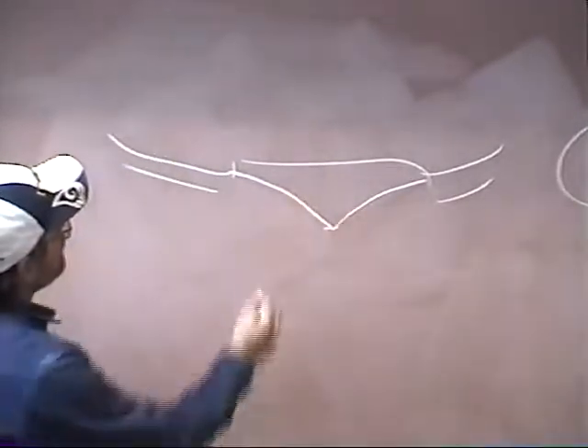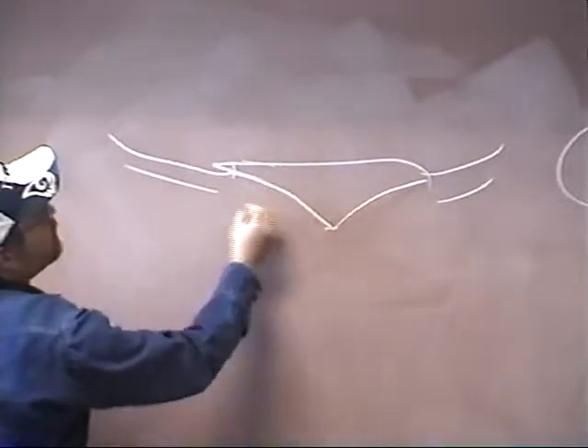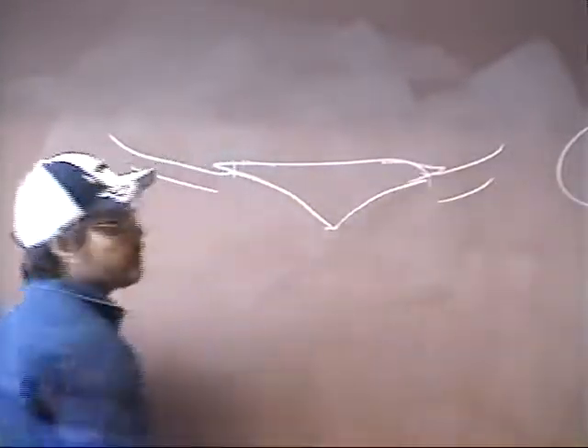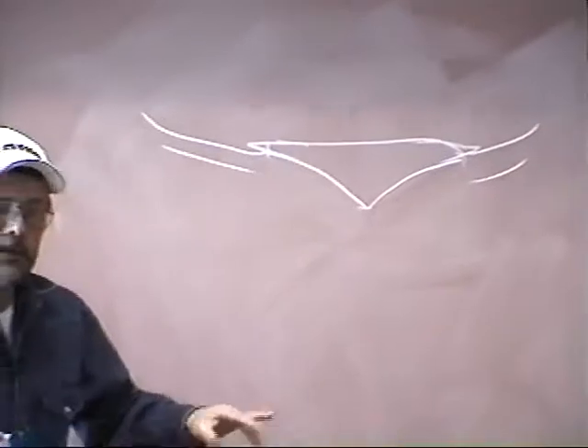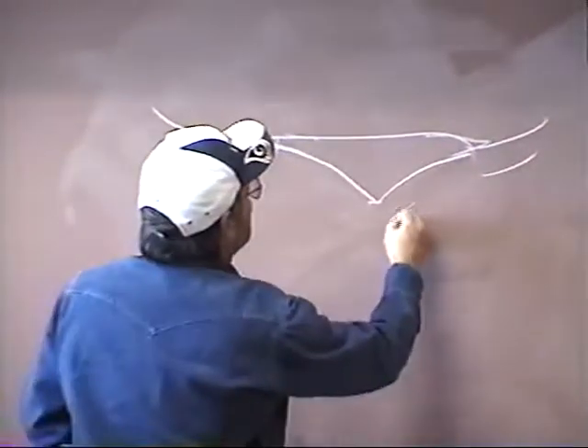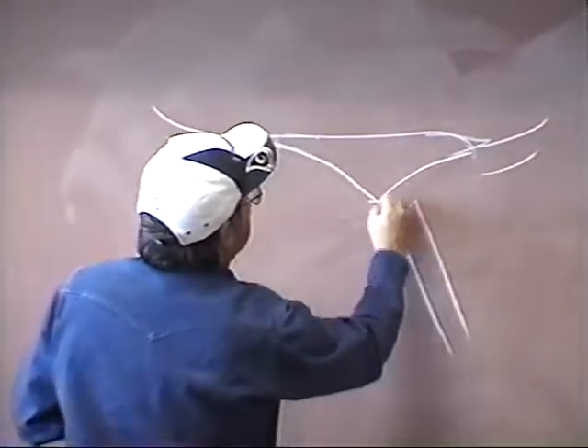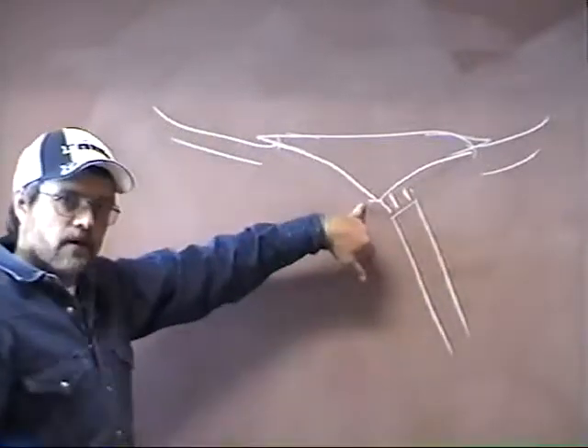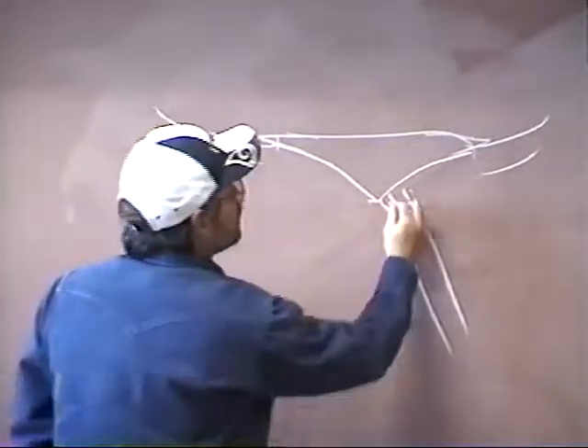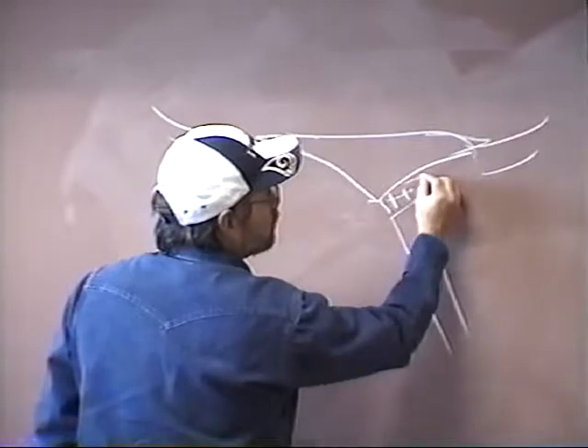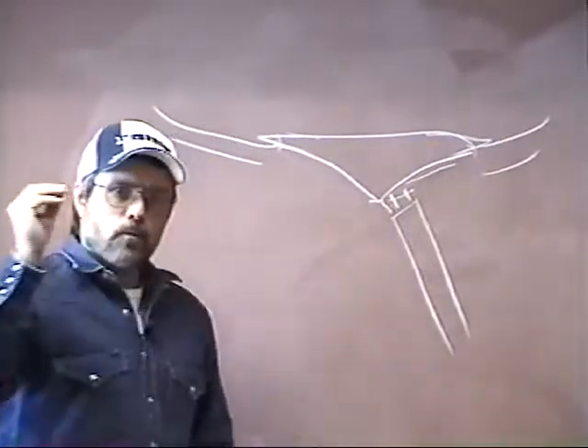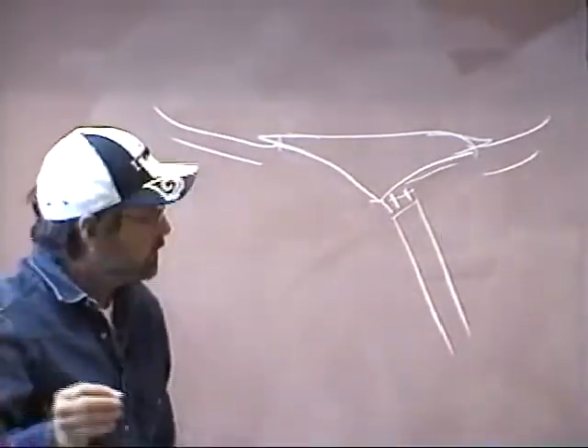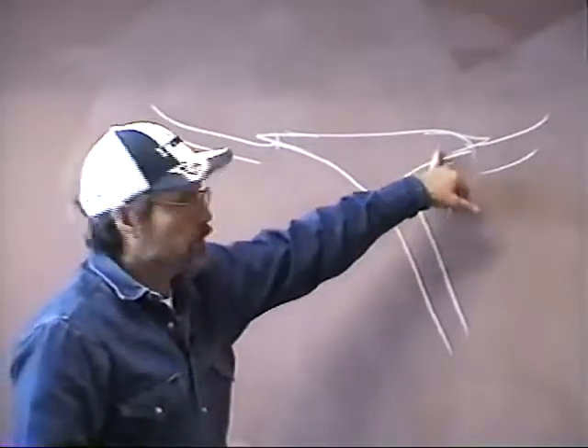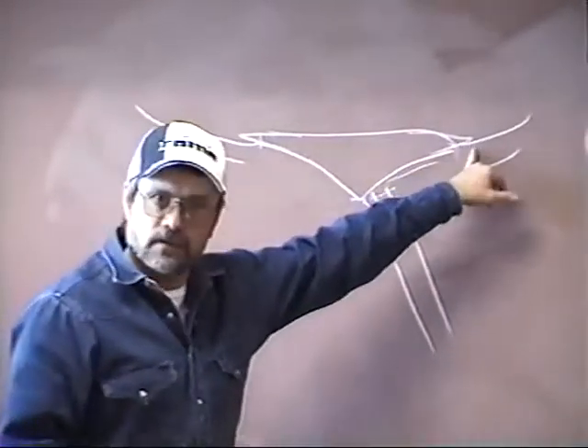By removing most of that thickness, now you come down to a nice feather edge on each end. Then when you go to weld, you're going to strike your arc right here at the peak of that grind, right there. And then you're going to come out slowly. Just walk out real slow. And what I want you to keep in mind, and it's very important, is that you burn through the tack before you reach the end of it.